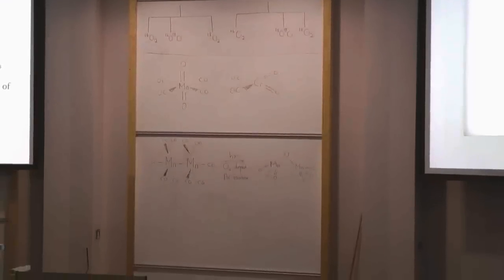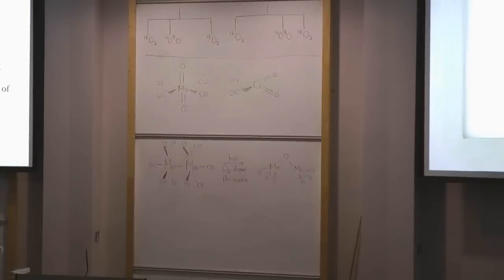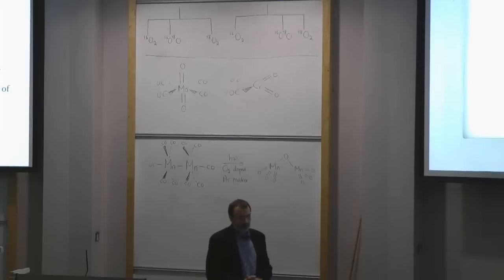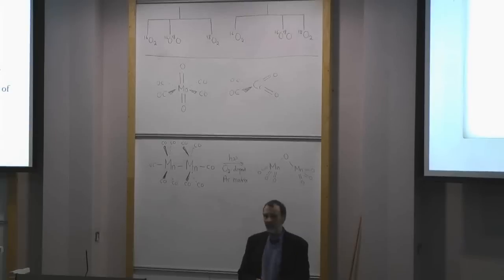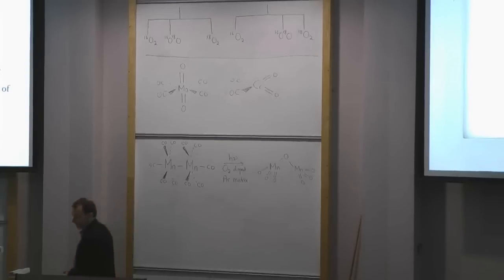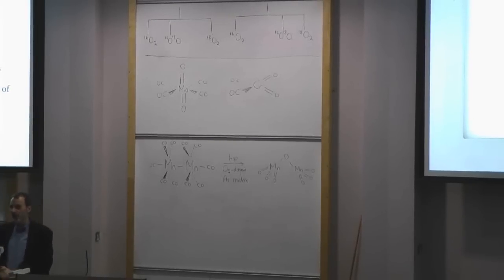And an interesting reaction that I looked at about this time is that we found if you take manganese Mn2(CO)10, a well-known organometallic compound, and you photolyze that in an oxygen-doped argon matrix, you could take off all the carbonyl groups and you could end up with Mn2O7, a well-known explosive compound, but reasonably safe if you make it in little bits in a low-temperature matrix. There's an awful lot of chemistry going on there, and I've never re-explored this, never looked again at what's happening, but you're breaking an awful lot of bonds and you're making an awful lot of bonds.